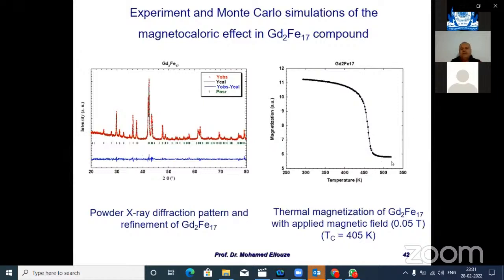Here also we have magnetization versus temperature, with an applied magnetic field of about 0.05 Tesla, and we can see that the Curie temperature is higher than room temperature, about 400 Kelvin.